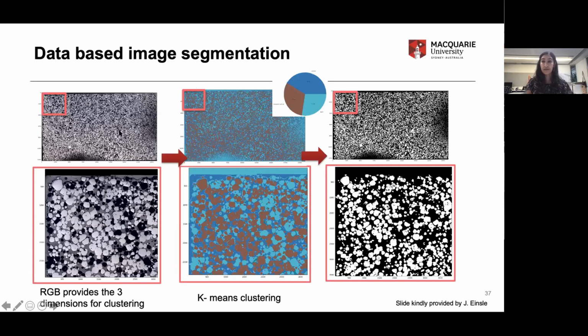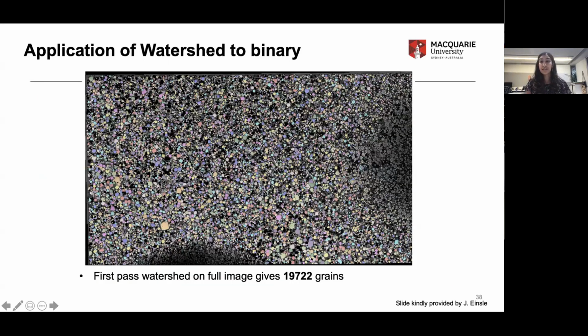So once we've uploaded our image and we apply the same smoothing filters, we use an approach called k-means clustering to identify where the grains are. In this case, the chromite are these brown grains. The holes, and there are a lot of these in this thin section, are these light blue areas. And the background blue, which we're not interested in, is this dark blue. And from there, we can binarize the image once we've made an estimate of what that red, green, blue channels are doing. And from there, we can apply the same watershed that we did earlier. And for this image, we're able to identify almost 20,000 grains. And we have grain size and all those other metrics associated with them.